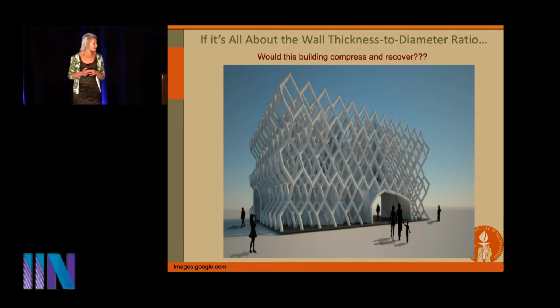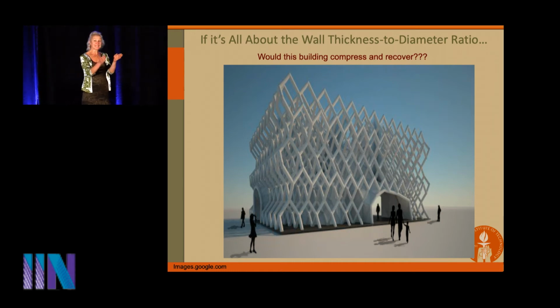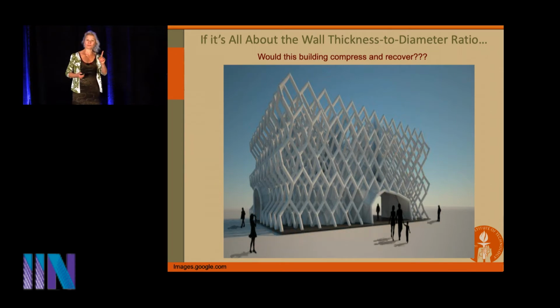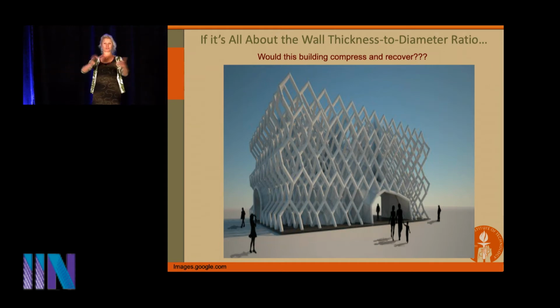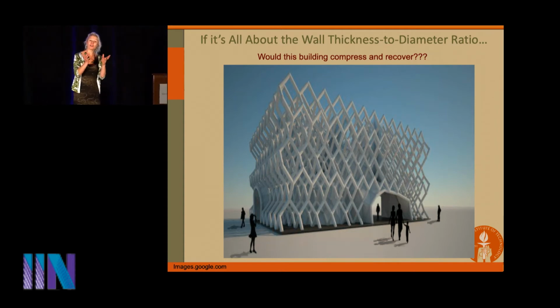So it turns out that the answer lies in defects. The probability of finding a flaw in something that's 10 centimeters thick is 100%. Not just one flaw, but millions of flaws. Any little micro-inclusion, any little void, any little pore. And then the local stresses at those defects will far exceed the globally applied stress. And so, of course, the material will always fracture before your structures ever get a chance to shell buckle. So this would never happen with such large dimensions because of our ability to make much more perfect materials when their dimensions are reduced to the nanoscale. So the size effect manifests itself here in our ability to make much higher quality materials.